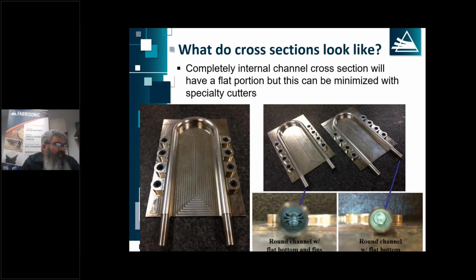Along the same lines, this is another heat exchanger, similar pedigree. And here we're trying to show that the internal passageways can be machined specifically to get different flow rates, different cross-sectional areas. The cross-section on the left, we just made a custom CNC mill. We had that milled for about $45, $50, and then we milled the internals of those channels just like any other channel, but we're able to get a lot more surface area, get thin structures. And then just like any of our other heat exchangers, we print a lid over top of that to seal that in.